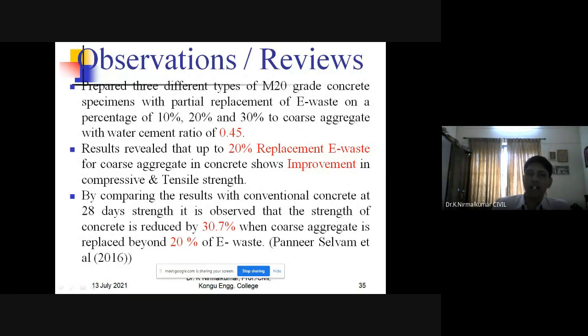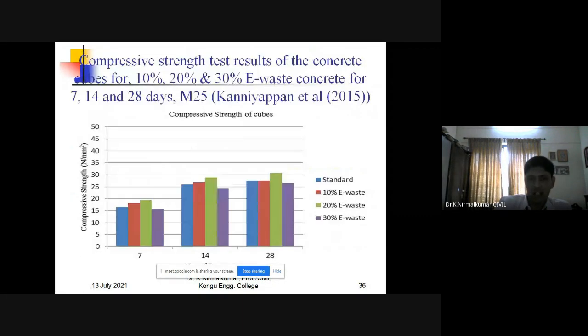It shows an improvement in the compressive and tensile strength. Because he replaced only 20%, that was not a big issue, but if we go for a higher percentage, we will have some issues. Comparing with the conventional concrete at 28 days, it was observed that the strength of the concrete is reduced by 30.7% when coarse aggregate is replaced beyond 20%. So he optimized up to 20%, and up to 20% he recommended the usage of e-waste replacement in the concrete.